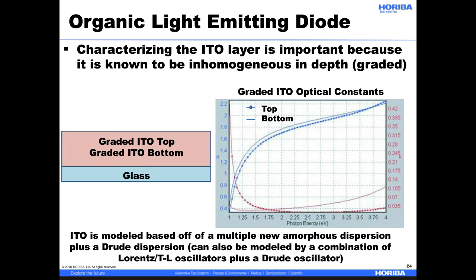What's also important for the organic light emitting diode is the ITO layer, mainly because it's inhomogeneous in depth, so we call it graded. It has an index difference from the bottom of the layer to the top of the layer. So what you'll see here is basically the graded ITO layer on top of glass and the resulting optical constants. The dots are at the top of the sample, the line is at the bottom of the sample. So we have some index change, a linear index change, as a function of where we are in the ITO layer. This ITO is also modeled based off of a multiple new amorphous dispersion, but now we've included a Drude dispersion as well for the metallic, conducting character. This can also be modeled by a combination of Lorentz or Tauc-Lorentz oscillators plus a Drude oscillator. So there are different ways you can model these samples.